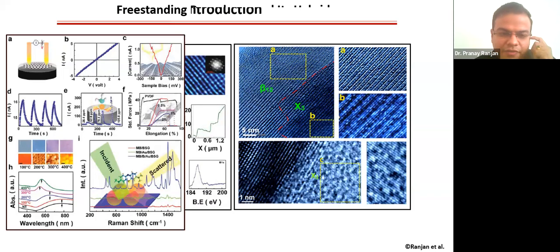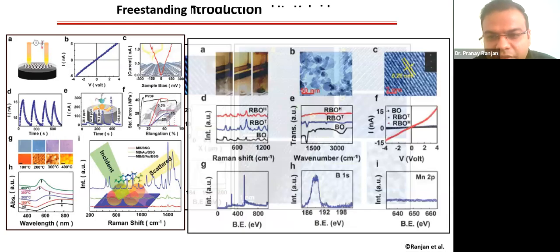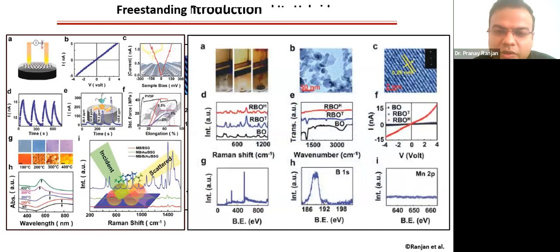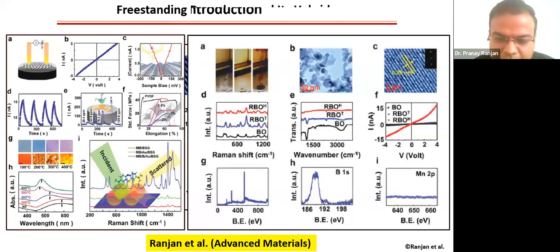We even tried different kinds of SERS platforms. What we found is that even borophene itself gives us a SERS platform. So this made us think about why this metal cannot be synthesized at large scale. Just like the analogy of graphene to graphene oxide, we tried to make borophene oxide through a chemical route, and we ended up with a pure phase of borophene oxide, and the scalability has changed from milligram to gram scale. So this report was published in Advanced Materials.